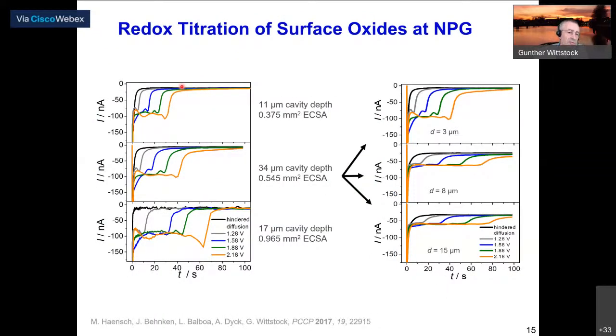Okay, the first test, of course, is to make this experiment with cavities of different depths. So we have here a cavity with 11 micrometer depth. We fill it. We go to different potentials, which are listed here, from lower to higher. And the higher we go with the potential, the more surface oxides are there, which we can titrate. If you take a deeper cavity, then we have more material in it. It takes longer until we have titrated everything, because we use a constant concentration of the mediator. But then if we take a 17 micrometer cavity depth, we see, oh, this has a different filling, because that filling is not perfectly reproducible, and we get different charges on that. However, we can determine the active surface area for each filling and then correct for that, and we will see later on that this gives very reproducible results.